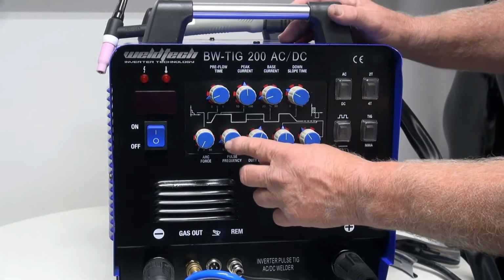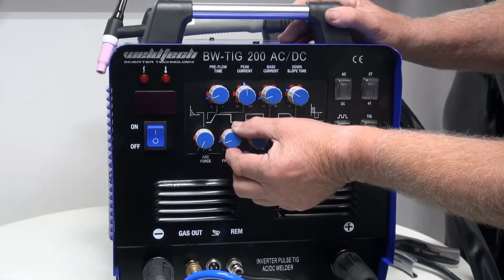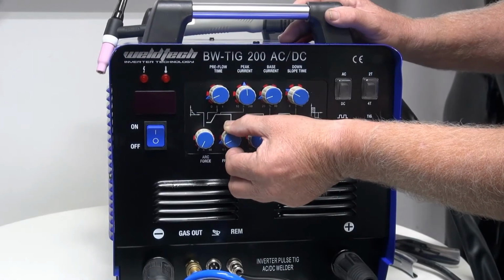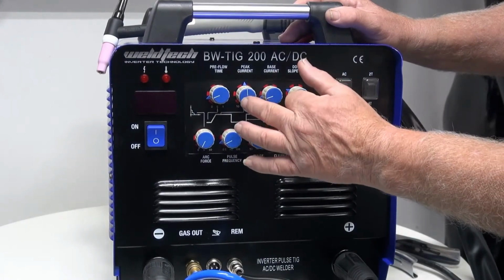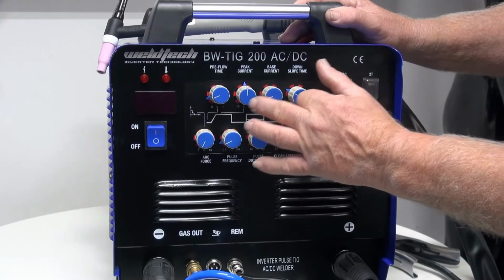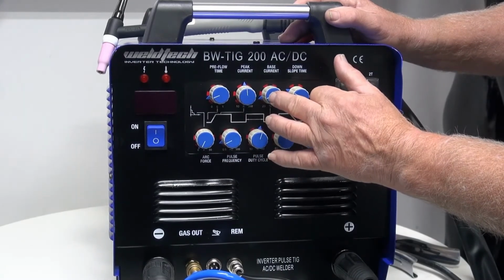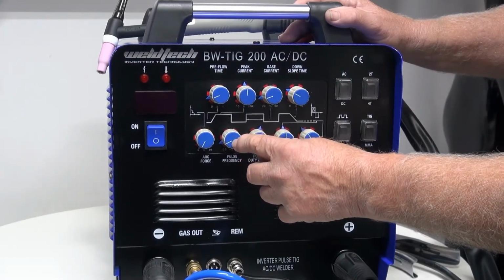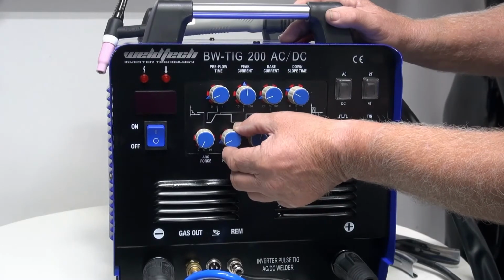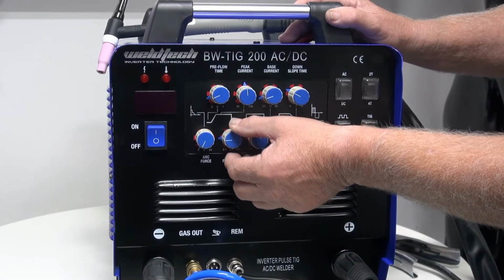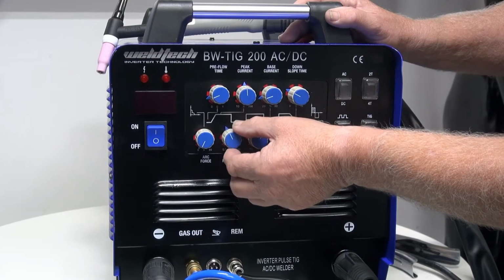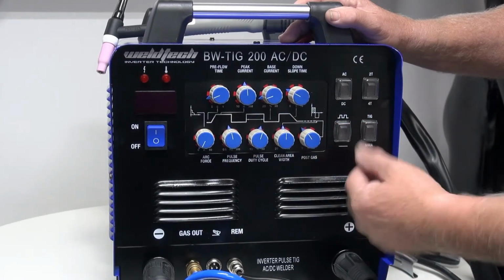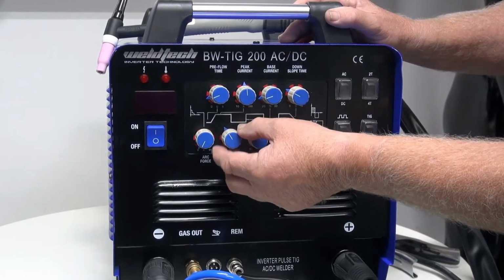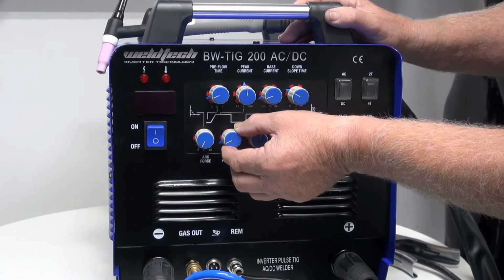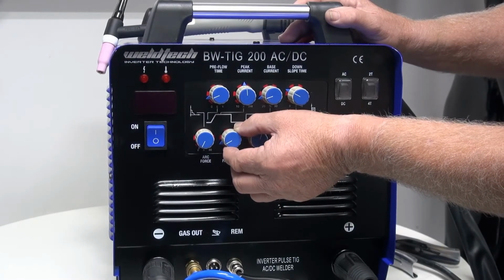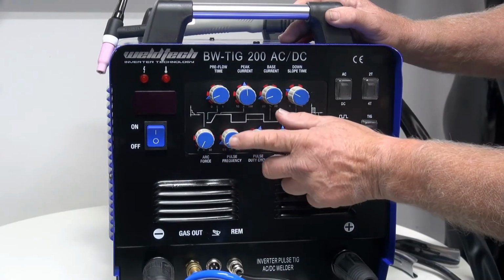Now we're going to talk about pulse frequency. Pulse frequency is this knob here, and it determines how fast we go from the peak current down to the base current. Peak current, base current. Quite often this is a personal preference. Myself, I quite like the pulse to run quite slow. More talented welders than me tend to turn the pulse up a bit. But to start with, I recommend you set the pulse at around 2 to 3.5 pulses per second, which is down there.